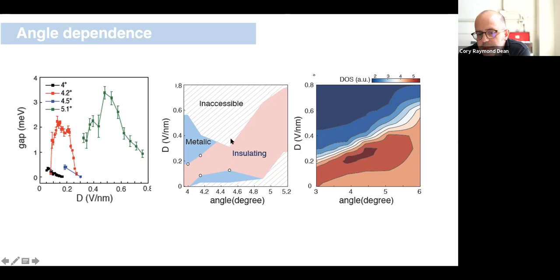So here we're plotting a representation of where the device is metallic, so where we leave this insulating regime, as a function of displacement field versus angle. And we see that roughly there's a locus of points that defines this pink region, defining where we might expect to see an insulator in our system as we vary D and vary twist angle. And then we went back to our theory collaborator friends and asked, can we generate a 2D map of the density of states at half band filling as a function of D and twist angle? And what we find is that there's, again, fairly good qualitative agreement between these two plots.